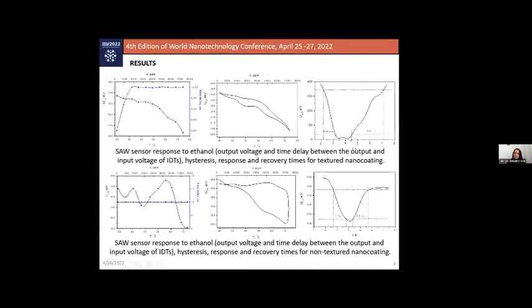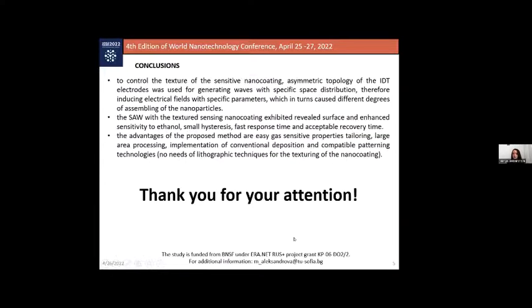Response time is less than a second, with acceptable recovery time within the current standards of other ethanol sensors produced by other techniques. And about the non-textured coating, you can see that the dynamic range is really narrow with limited absorption capacity, because the linear region is beyond 5,000 ppm, and before that there is no stable interaction between the analyte molecules and the coating. It has a very broad hysteresis, which introduces approximately 5% error in the measurements. The timing characteristics are good and similar to the textured nanocoating, but except for them, there are no other benefits of using the flat surface.